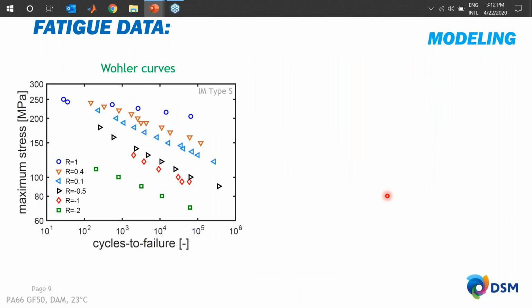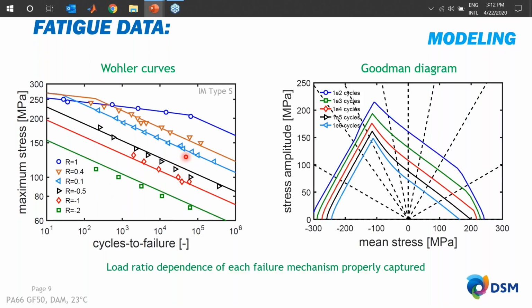And to demonstrate this, you can see here the fatigue data that we measured on this polyamide 66 with 50% glass fiber. You can see the maximum load versus the number of cycles, so the typical SN graphs, for R = -2 ranging up to R = 1. So let's say creep rupture up to a very large tension-compression load. And then if we compare our models calibrated on these data points, you can see that our models describe the experimental data points very well. Logical, because we also use these to calibrate a material model.